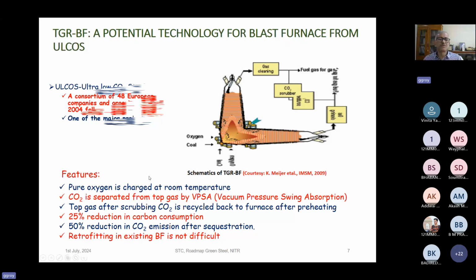It has been found you can reduce carbon consumption in the blast furnace by 25%, and CO2 emission by 50% if you do the sequestration. Whatever CO2 you are scrubbing, if you sequester it by liquefying it and storing it somewhere, then you can reduce the CO2 emission by 50%. And you can simply retrofit it to an existing blast furnace. It's not very difficult. Only the preheated air blast should be replaced by oxygen.